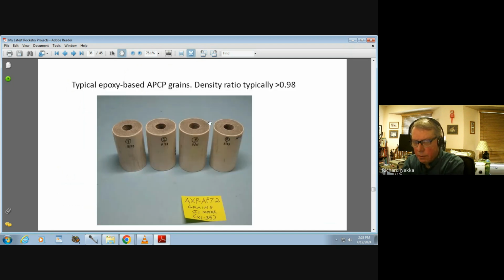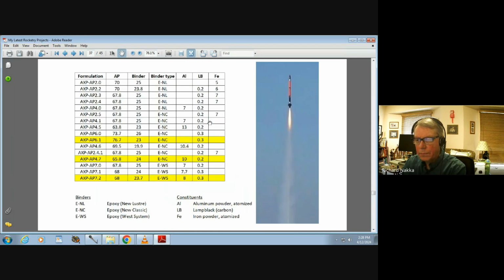So this is a photo of some typical propellants that I've prepared. Density ratio is typically greater than 0.98. And over the next while, I managed to develop quite a few different formulations using epoxy. I've used 3 different binder systems. I've used the New Luster epoxy. I've used a similar one called New Classic. And I've even been successful in using West system.